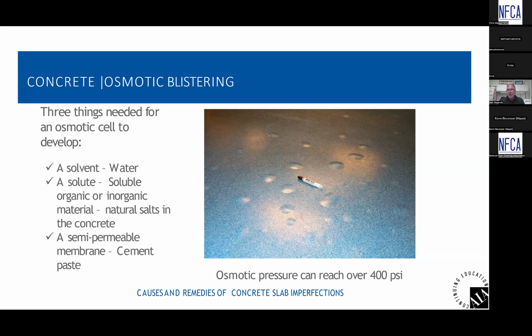And if we still are in a situation where we have that liquid water coming up, and maybe we still have high salt levels, with that different cementitious material on the surface of the concrete, the water and the salts can flow up into the new leveling material and can move around and can go back down, because there's no semi-permeable membrane in that new material that was placed. So it's a laborious application to remediate osmotic blistering situations, but a proven industry practice.